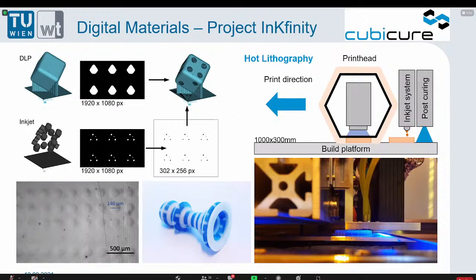So we were able to modify the thermomechanical properties and increase the toughness of structures by selectively placing weak interfaces, for example. But the project I'm presenting here is more or less an enhanced version of what we did in those former projects. For this, we worked together with Cubicure, where we combined the inkjet with a new hot lithography process of Cubicure. Cubicure has a new large-scale process, which enables quite a few things. I cannot go into detail right now. You will see a lot more in a few months. But so far, I can say that this process is continuous, and it has quite a big building platform of 1 meter times 300 millimeters.